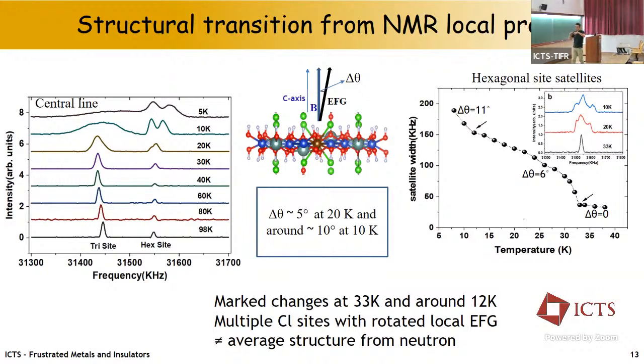It seems that the small distortion, the small change of the hydrogen position, is actually giving different kinds of hexagon, but there is no spatial correlation between this distortion, and on average, the symmetry is maintained, basically. Okay. If we want to quantify this distortion a little bit, we can attribute the splitting to a change of the EFG, the electric field gradient, so the electrostatic structure around the chlorine, by 5 degrees at 20K and an additional 5 degrees at 10K. So there are probably small changes, but with some kind of disorder, you would say, with no correlation in the plane.